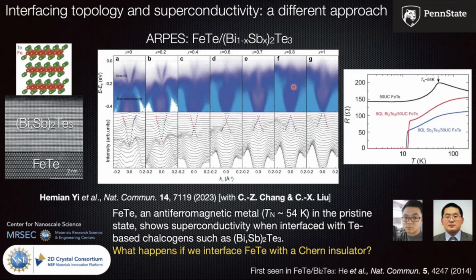He said that, look, something like a decade ago, there was a very interesting paper published by a group in Hong Kong that if you grow iron telluride, which is an antiferromagnetic metal, and you grow bismuth telluride on top, you get a superconductor. So neither iron telluride nor bismuth telluride is a superconductor by itself, but you interface them and you get a superconductor.